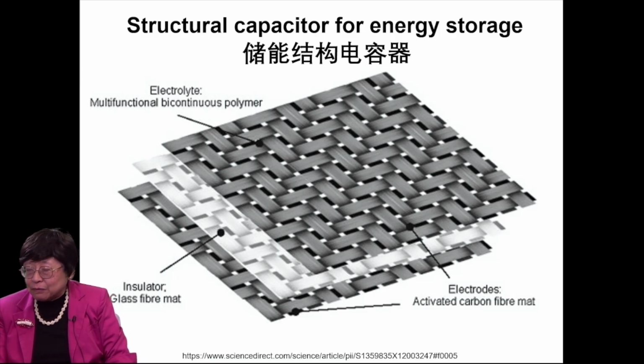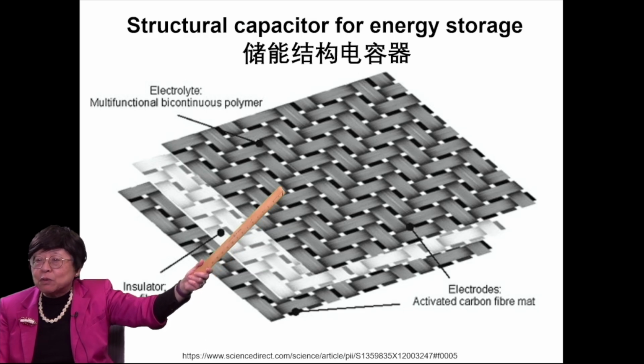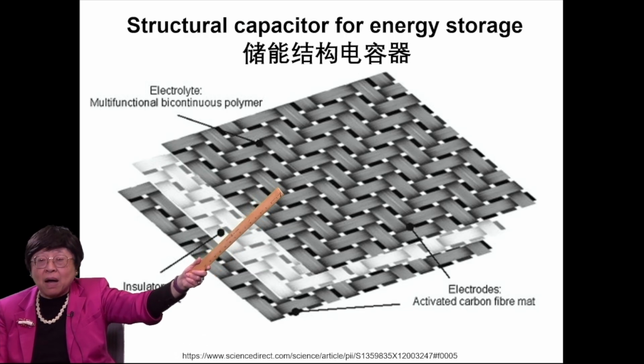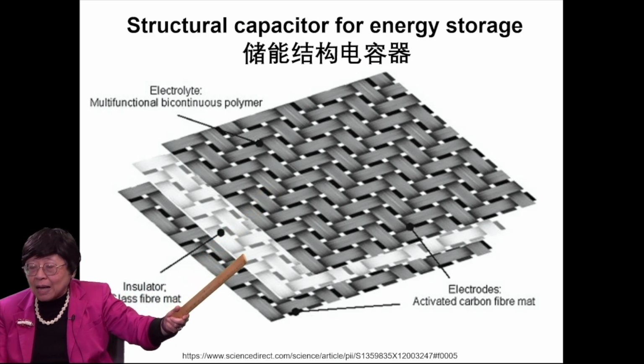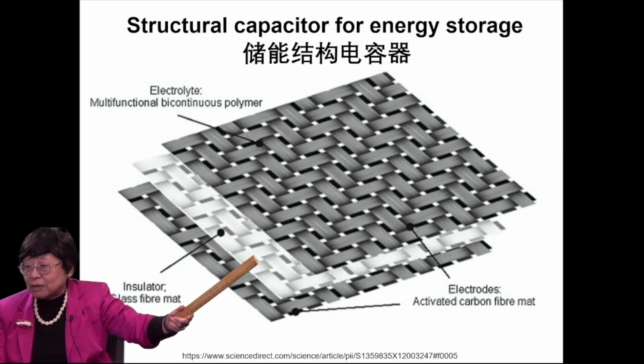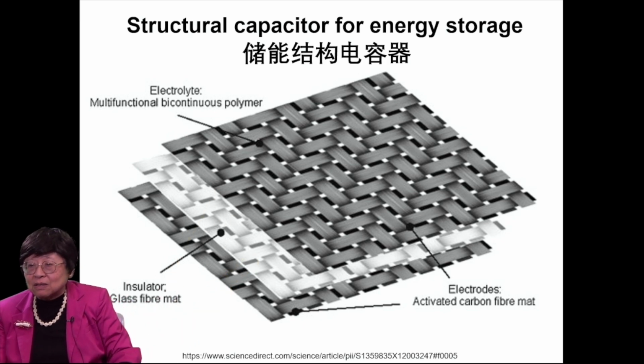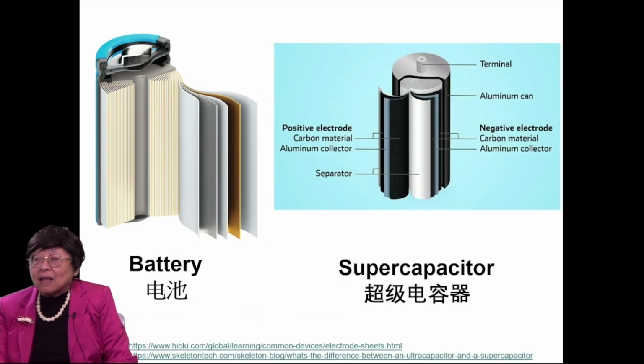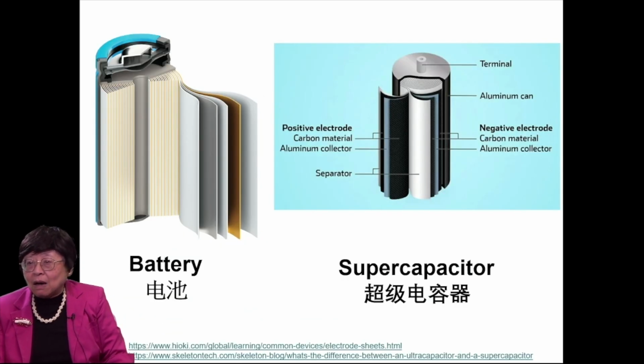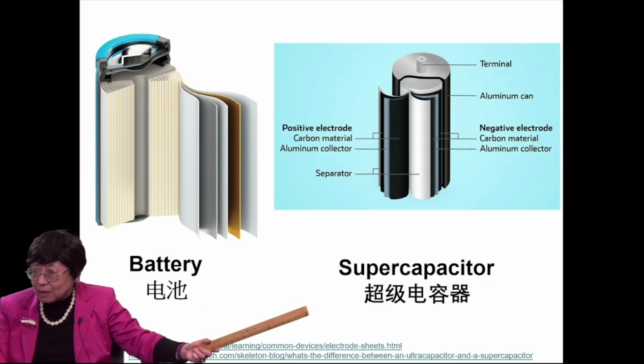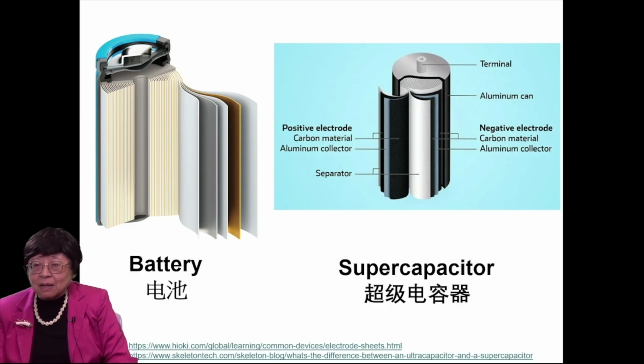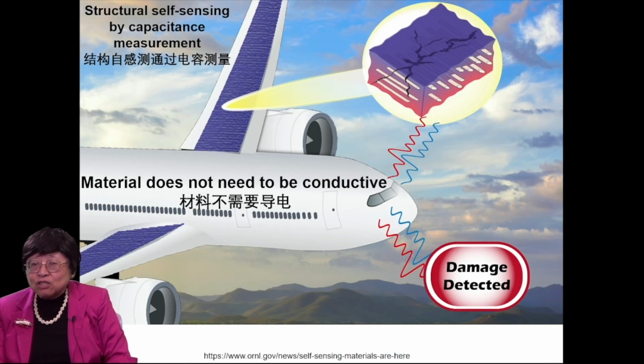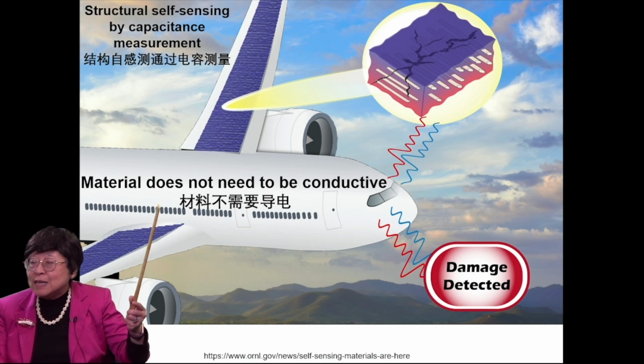One can have structural capacitor for energy storage, say by using some conductive part of the structure composite as the electrode, and other parts that are non-conductive as the dielectric, being sandwiched by the two conductor sheets. The permittivity is also very important for battery and supercapacitor, particularly the electrolyte in these electrochemical devices. In addition, we can have structural self-sensing that's based on capacitance measurement as opposed to resistance measurement. The nice thing about capacitance measurement for structural self-sensing is that the material does not need to be conductive.